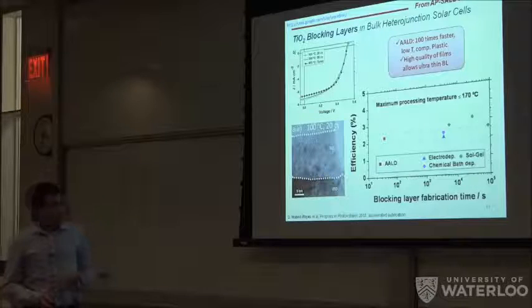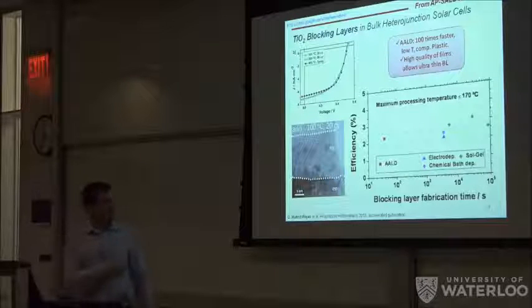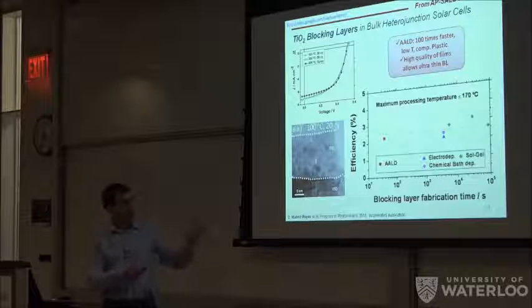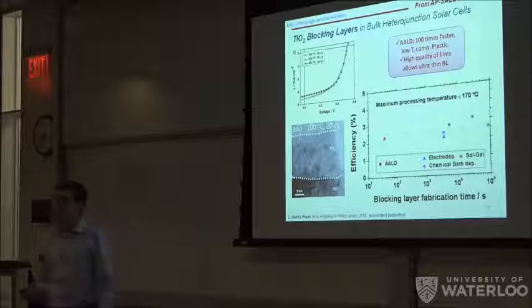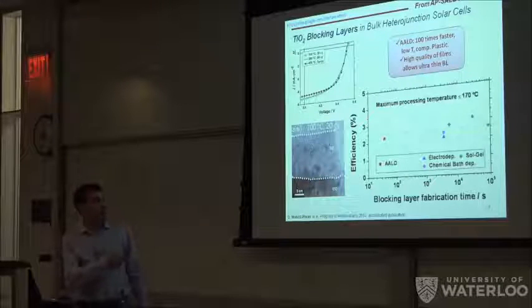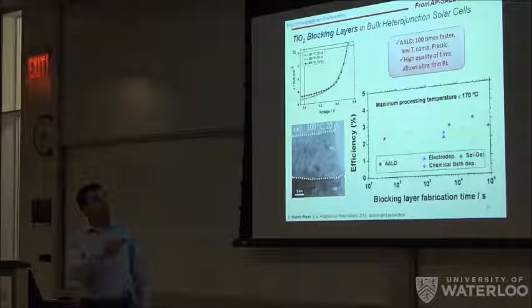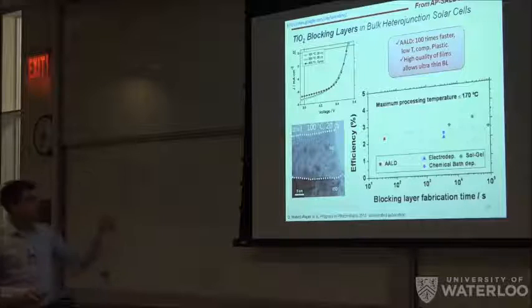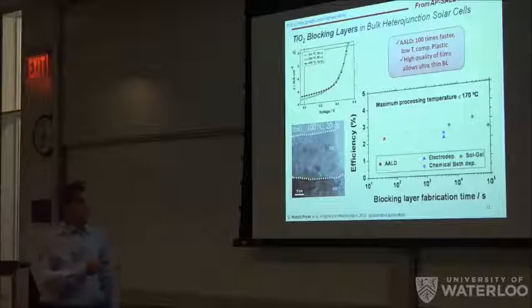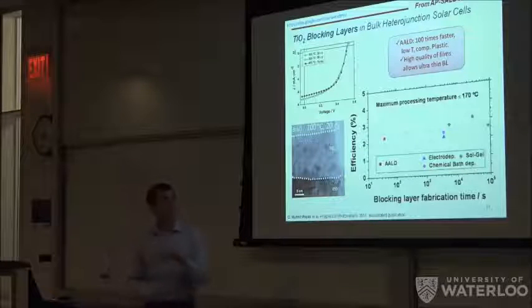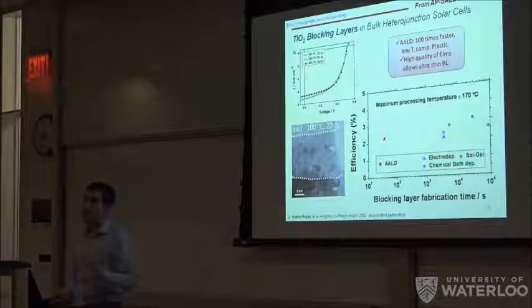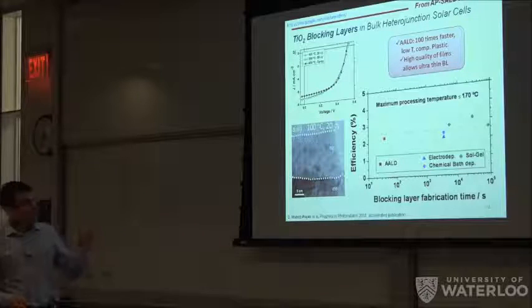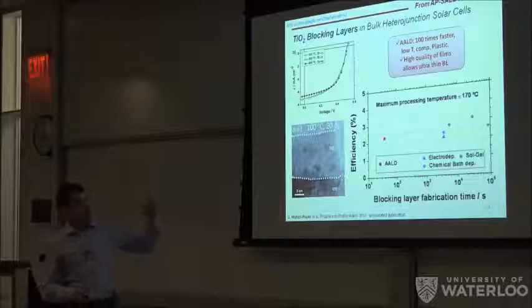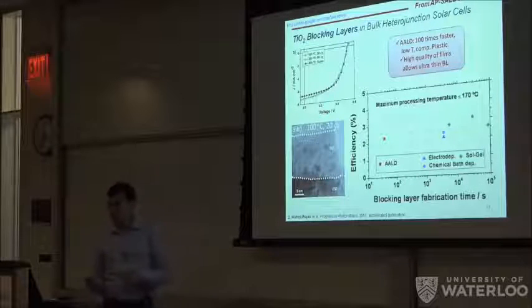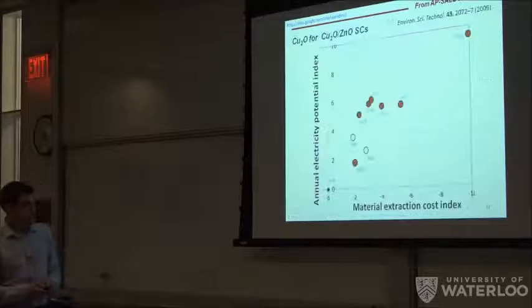And the other thing that has to be noted here is that we have a 15 nanometer layer of TiO2, which is amorphous, so conductivity should be awful. And we're still able to do a solar cell which doesn't have a huge series resistance because we're using a thin layer. And we're able to use a thin layer because the layer is perfect. It's crack-free over centimeter scale again. So this technique allows us to use a very amorphous, low temperature growth layer, very thin, which is still able to perform really well. So it's quite remarkable.